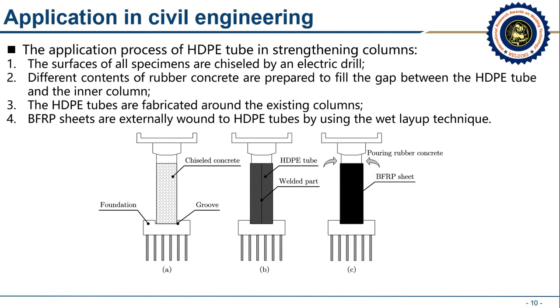For HDPE tubes, as shown in Figure 1, this new form comprises the HDPE tube as a permanent protective shell. A basalt fiber reinforced polymer wrapped around the HDPE tube and interfered rubber concrete between the existing columns and the HDPE tube. According to the technical characteristics of thermoplastic HDPE tubes that can be hot welded on site, HDPE tubes are vertically split into 2 parts and welded up around the column. This is for the strengthening of existing concrete piles and columns with BFRP wrapped outside HDPE tubes with interfered rubber concrete.